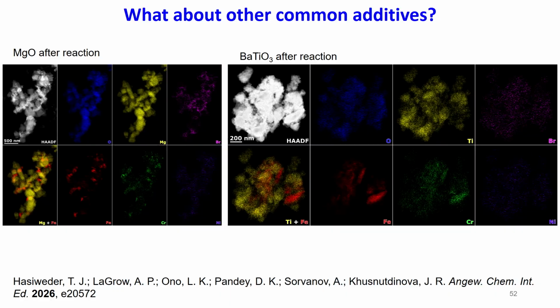And it doesn't happen just to zeolite. It basically happens to any solid insoluble additive that you add into the mechanochemical reaction mixture. So the same thing happens with magnesium oxide. You again have these patches of iron and chromium. The same happens with a very popular reagent, barium titanate. It also gets covered in iron and chromium. And finally, that explains our mechanism. So the actual reductant for our nickel catalyst is most likely the zero-valent, freshly exposed iron or zero-valent chromium present in the steel, which reduces our nickel catalyst and activates it towards entering the catalytic cycle.